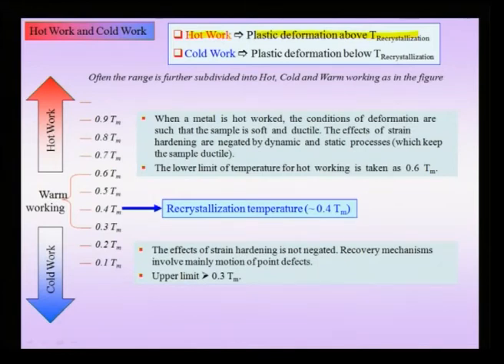On the other hand, suppose you do plastic deformation below the recrystallization temperature, it is called cold work, and this range can further be subdivided into 3 regimes. Typically, recrystallization above 0.6 Tm, I can call this hot working. If I do it in the low temperature regime below 0.3 Tm, then I call it cold working, wherein my material becomes a battery of energy, the defect density increases. That means that in the cold working regime, the effects of strain hardening are not negated, recovery mechanisms involve mainly motion of point defects, and my material tends to accumulate these defects and its ductility would reduce, but its strength would increase.